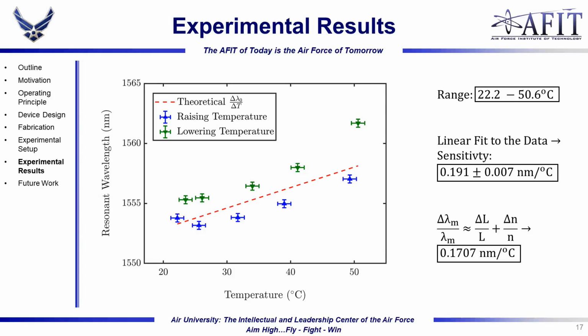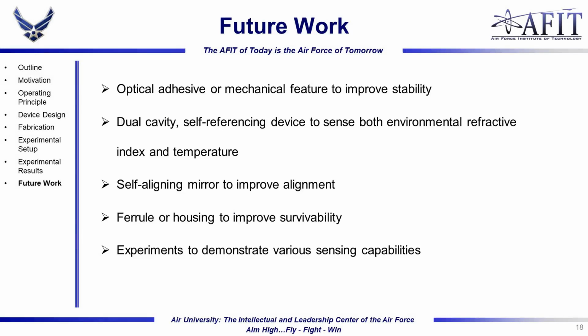A significant degree of hysteresis is present in this data, which we attribute to the mirror resettling after initial expansion into the clearance between the pin and its housing. This would explain the consistency of the offset between the two measurements. Stabilizing the device to remove this clearance is on the top of our list for future work. Our current ideas include locking the pin with an optical adhesive or fabricating a mechanical structure such as a cam or shim to hold the mirror once it is lowered.